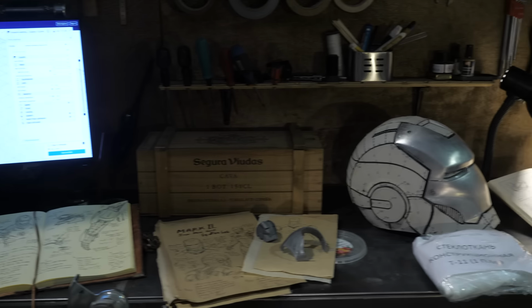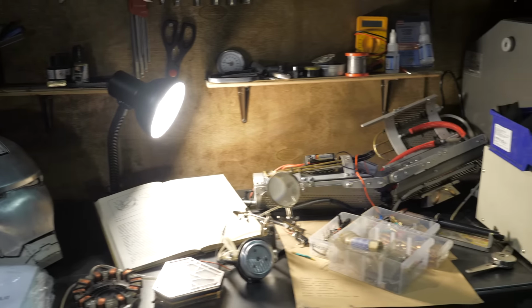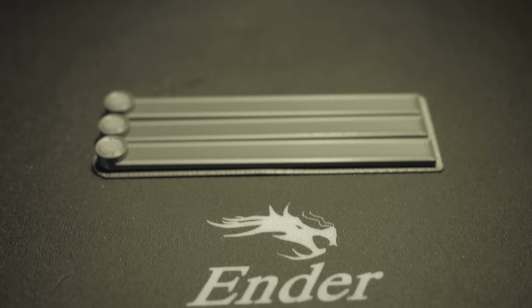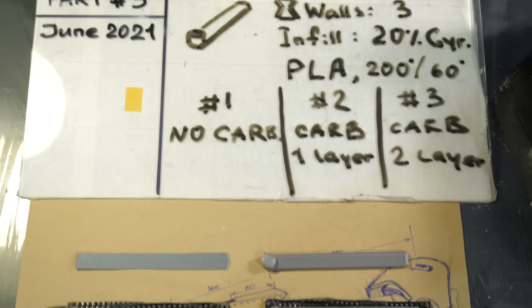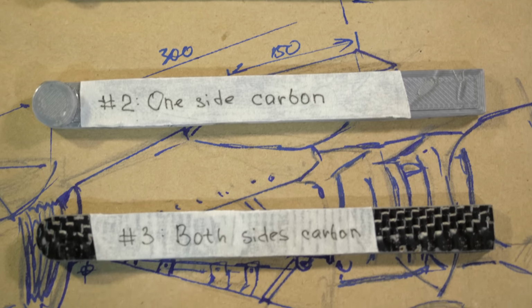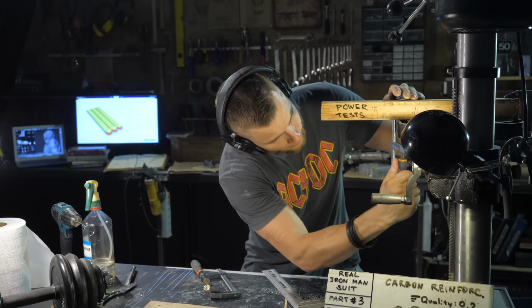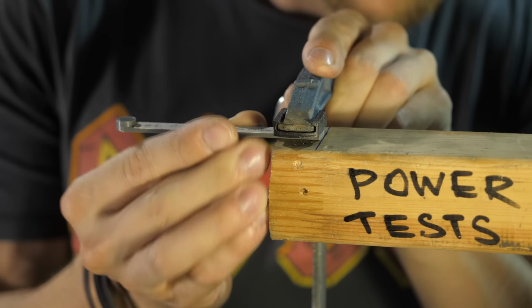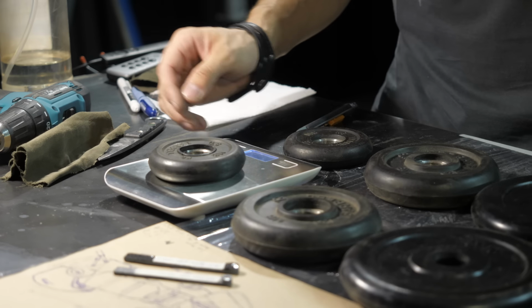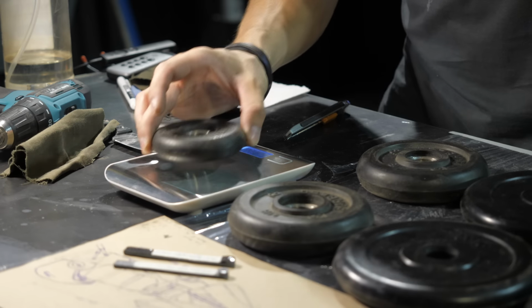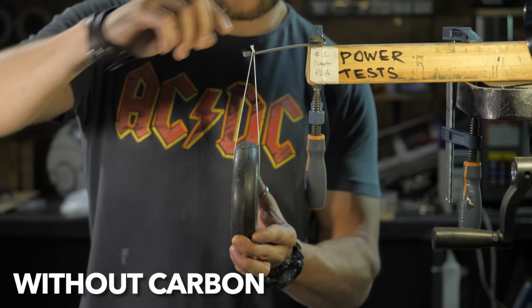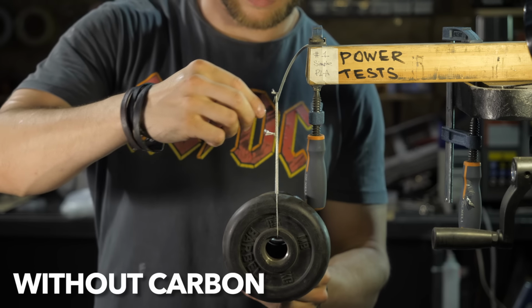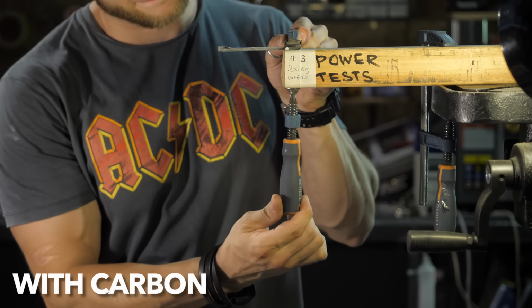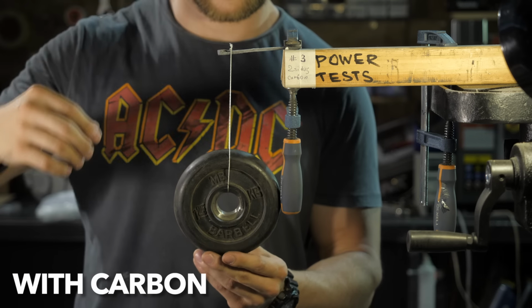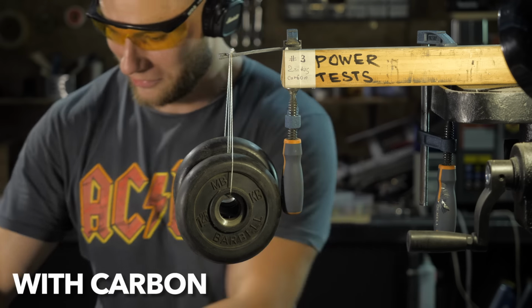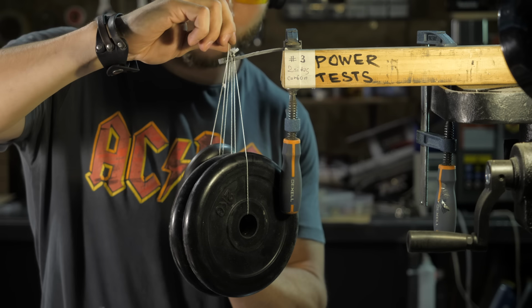Before reinforcing the parts of the suit, I wondered how much stronger the parts will become if they're reinforced with carbon. I tested the PLA parts and the same PLA parts reinforced with carbon and epoxy resin. With good gluing, parts that could only support 1.5 kg could withstand 4.5 kg of fracture load.